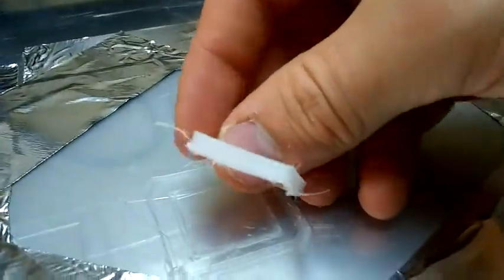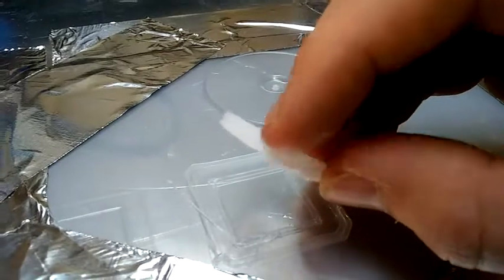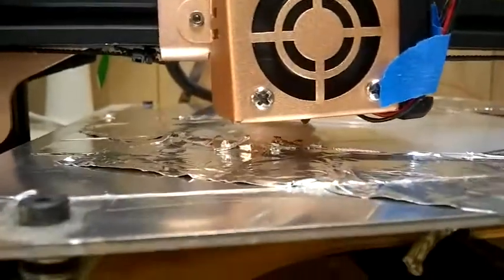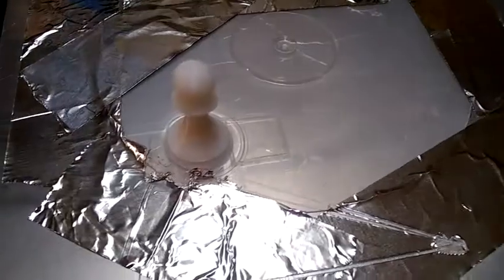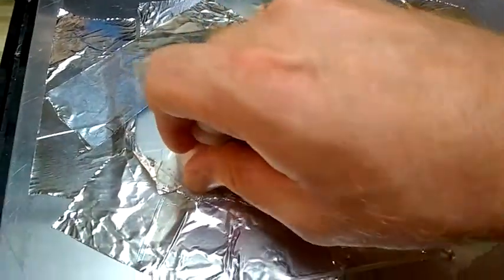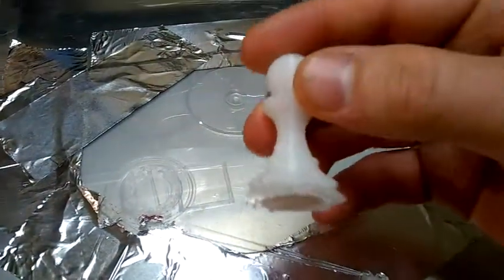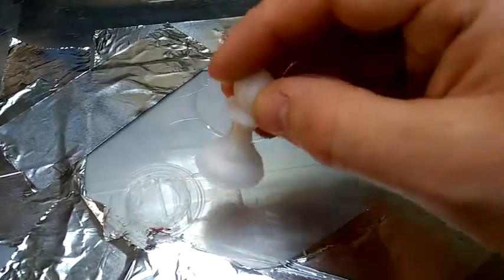It comes off a little bit easier than the HDPE substrate, which is kind of nice. I was able to peel it off with my hand, which is next to impossible when it's fused on the HDPE sheet. This is HDPE printed onto polypropylene and it comes off pretty well — actually much better than printing HDPE on HDPE. I hope you enjoyed and thanks for watching.